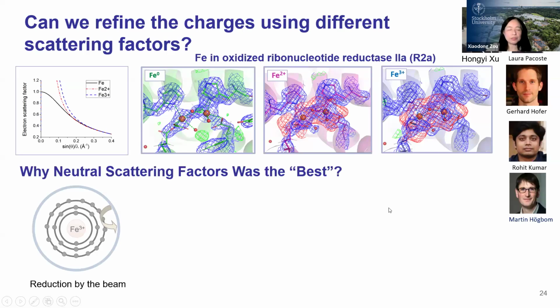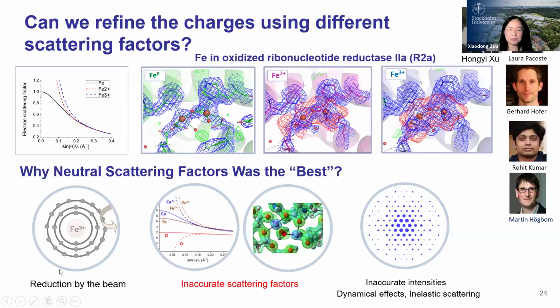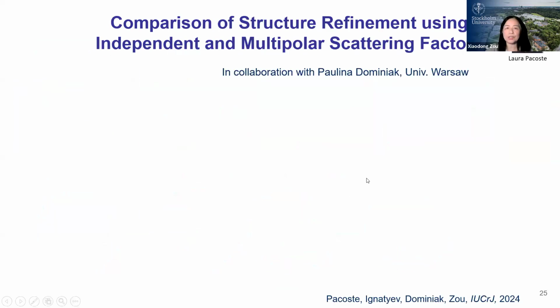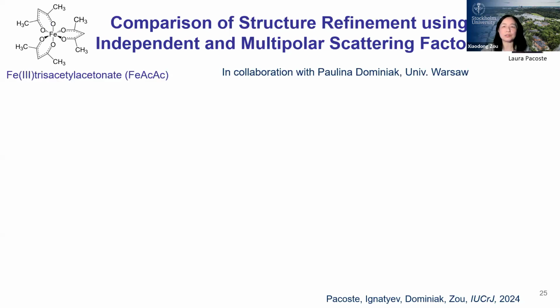But why? We wanted to find out, is it because of the reduction by the beam? Is it because the scattering factors are wrong? Or is it because our data is not good enough? And for all these, as we showed using micro electron diffraction, we have minimum beam damage. So we went to look at whether there is a better way of modeling the scattering factors. The current scattering factors we use mainly treat independent atoms, so atoms do not really interact with others. Because this method doesn't really work with proteins, we started with a small molecule.